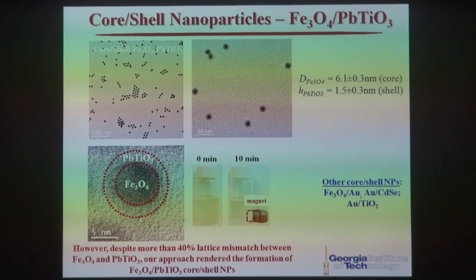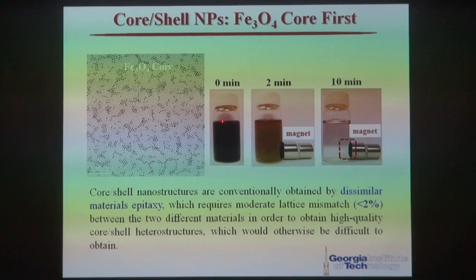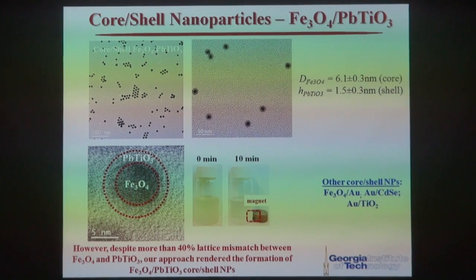and the thickness of the coating is about 1.5 nanometers. So now if you look at this digital image, originally we had a dark magnetic iron oxide nanoparticle solution. Once the particle is capped by lead titanate, the solution became translucent. However, when you apply a magnetic field, again, it became transparent. So this is the core-shell nanoparticle. In addition to this particular core-shell nanoparticle, we also made other sets of core-shell nanoparticles, including magnetic iron oxide core capped with plasmonic shell, plasmonic core capped by luminescent selenide shell, plasmonic core capped by semiconducting titanium dioxide